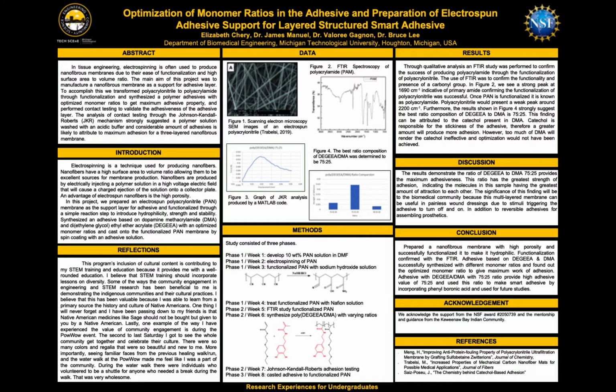So once we had conducted the JKR analysis, we then needed to run a MATLAB code that will allow us to produce a graph to visualize what we were working on. So in figure 4, we can see that there's a comparison of the strength of adhesion. So once I have the MATLAB code, I worked with the force that it produced and the surface area that it produced to calculate the strength of adhesion. And in this figure 4, we can see that the ratio 75 to 25 had the greatest amounts of strength of adhesion. So to conclude, we can confidently say that the ratio 75 to 25 provided the maximum adhesiveness.